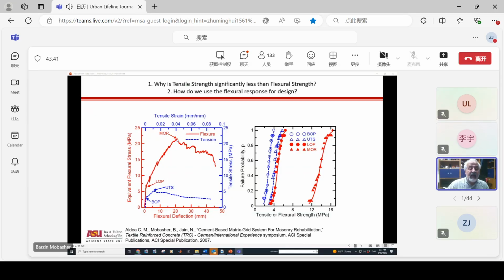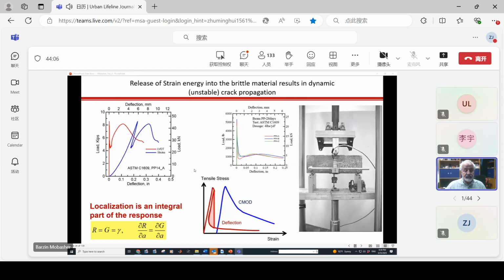So the challenge that we have is how do I use a material that I know its tensile strength is 5 megapascal, but design it so that the apparent flexural strength is about 20. That's the key point in our work. Otherwise, we're going to have a lot of bridges that are going to fail because somebody thought that just because I tested it in flexure and got 20 megapascal, I can apply 20 megapascal in tension also.